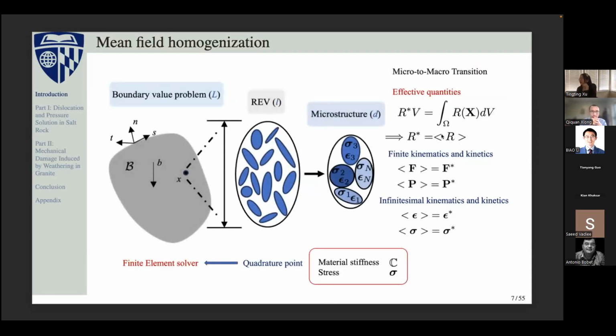The method that we used in this study, we call the mean field homogenization. So you can see that instead of using different numerical tools, which is time consuming, we consider the micro to macro transition as the integration of the effective quantities. If you look at the equations here, you can see that the effective quantities of the whole REV can be considered as the volume integration of these quantities. So if we consider the large strain or finite strain, we will have the kinematics and kinetics. We can take the deformation gradient as the volume average of the local deformation gradient, and also the PK stress as the volume average of the local PK stress.